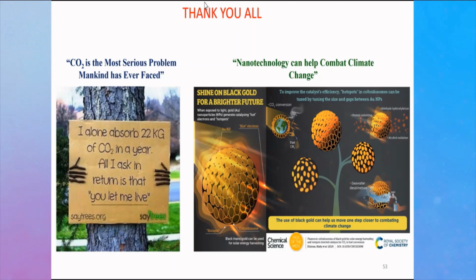Arkajyoti Chakraborty asks: are these black gold agglomerated gold nanoparticles which are used for the application? One can say that, because there are also black gold examples where people agglomerate rod-shaped particles and you get a black gold. The idea here was to keep a gap between the gold nanoparticles, and that gap is some sort of a nanoreactor. That gap is where I have a concentration of the thermal hotspot and the electromagnetic hotspot. So when my CO2 goes there, it will get that thermal energy, as well as experience that electric field, which will bend and activate the CO2. That was the idea. So it's not really agglomerated.